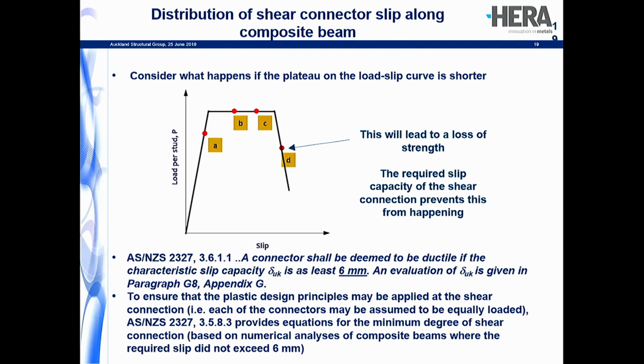If we didn't have that plateau, things wouldn't look so nice, in that essentially, as we get towards the end of the beam, you would start to get an unloading effect. This is why it's so important that, as well as resistance, the ductility is very important. So the magic number used in most design standards, and also included in AS/NZS 2327, is that the characteristic slip capacity must be at least 6 millimetres. If it's below that, the shear connector would be considered non-ductile.